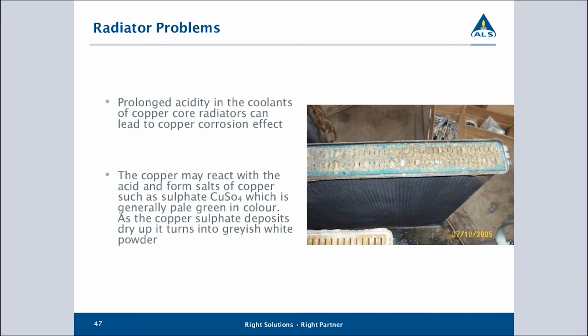All right, some examples of what tends to go wrong with the coolant. What we're showing on screen here is a formation of copper sulfate. To do this, we've got copper in our radiator cooler core, and if sulfur or sulfur compounds have got into the cooling system, they can react to form this greenish, bluish powder. It turns white as it dries out. Obviously, forming this is not good in our system. It will damage the tubes, so the copper becomes weaker as a result of this reaction. And then this material can become abrasive and also inhibit water flow by blocking up tubes in the system.